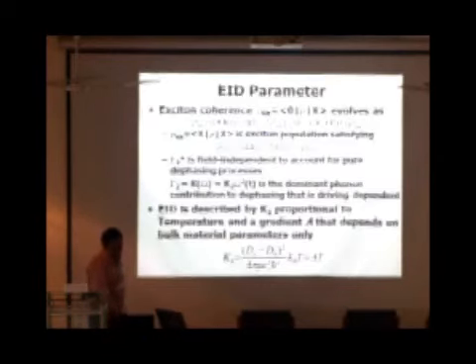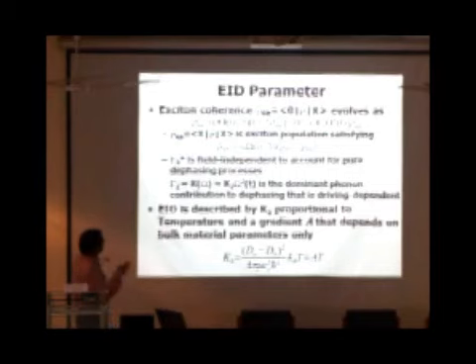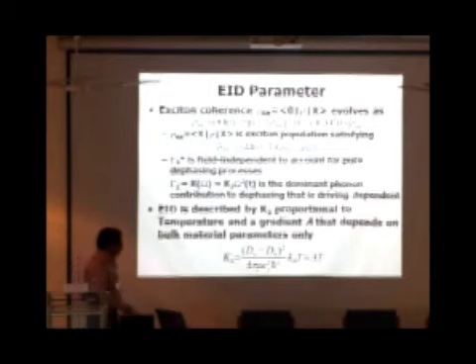If you look at the excitation induced dephasing parameter, you do all the math and you get essentially a K2 parameter which depends on the material, the bulk parameters, and the temperature. So we have a linear dependence with temperature expected for the dephasing induced parameter.